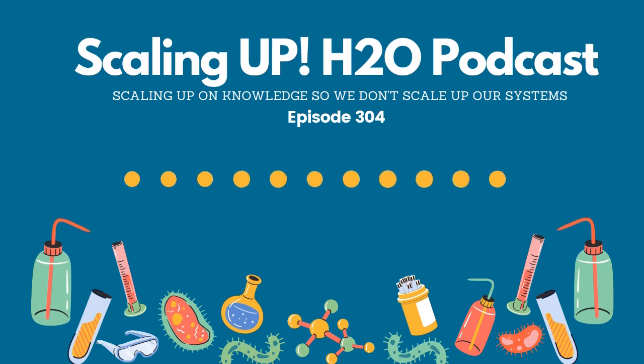Corrosion coupons are very simple. They are pre-weighed to the 10,000th of a gram. Folks, if you're wondering, that is four places after the decimal. So we really want to zero in on exactly what the weight is when we start. We then let that stay in the system for a certain amount of time. We're going to talk about that in a moment. And then we clean them up and then we weigh them. And then based on what the results are, we're going to change our program or we're going to keep doing the exact same program because now we have data from the corrosion coupons.